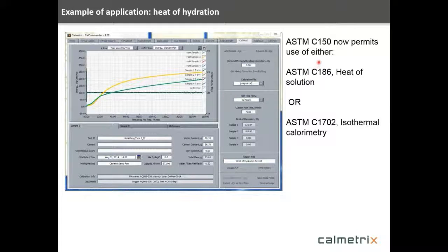So ASTM C150, you may or may not be aware, now allows you to do this test either using the classical technique of C186, which is a heat of solution technique, or you can now use the ASTM C1702 technique. So C150 now permits you to use officially either of these two techniques. Many of our customers are turning to isothermal calorimetry to do this experiment in lieu of the heat of solution technique. The reason is that the heat of solution technique uses dangerous chemicals, is a wet chemistry technique, and requires quite a bit of training with operators. C1702 and isothermal calorimetry is much easier.